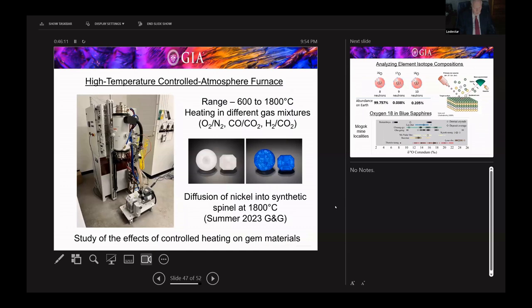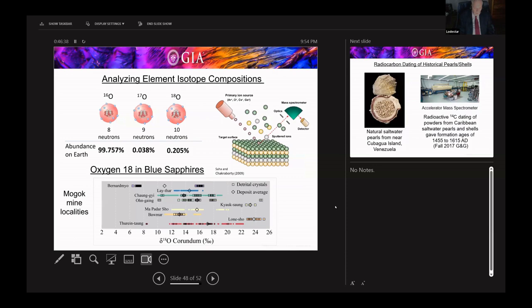We also have a high temperature furnace where we're able to do heating experiments up to high temperatures, kind of controlled heating on gem materials. And this is just an example of some of my colleagues. We tried taking a synthetic spinel colorless material and diffusing nickel into it and producing this kind of sapphire blue looking color. One of the newer things we're looking at now is analyzing isotopes.